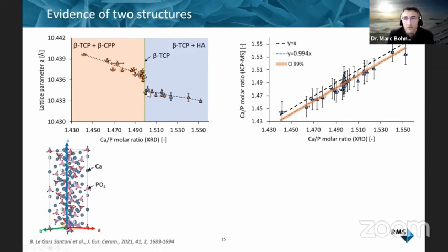And so we thought maybe it's a solid solution that happens. We looked at the calcium to phosphate ratio by ICP-MS versus X-ray diffraction. And if we had a solid solution, we would expect a jump somewhere, but we see no jump. It's perfectly linear.